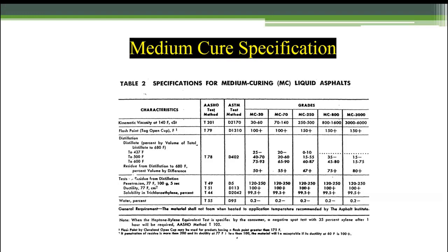Then they run a distillation. You can see that on the line down at the midpoint; again, one point to always look at is residue from distillation, percent volume. So an MC30 has roughly a minimum of 50% residual asphalt. The other 50% is diesel. If you're shooting an MC250, you want enough solvent to draw that asphalt down in to protect your aggregate base, but you also have to understand the time component. It doesn't become residual asphalt until that diesel evaporates. And it's essentially two-thirds residual asphalt, one-third diesel for an MC250. Again, the next line down is penetration of that residual asphalt. You can see in an MC, the pen graded rating on that residual asphalt is all 120 to 250 pen asphalt.